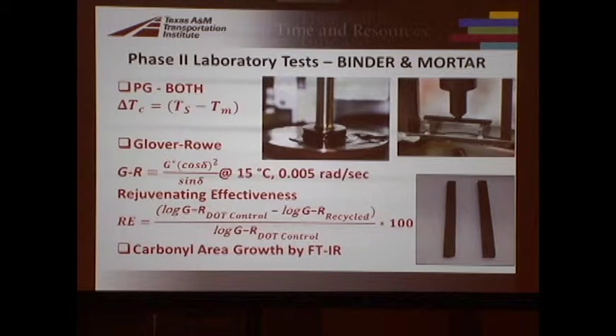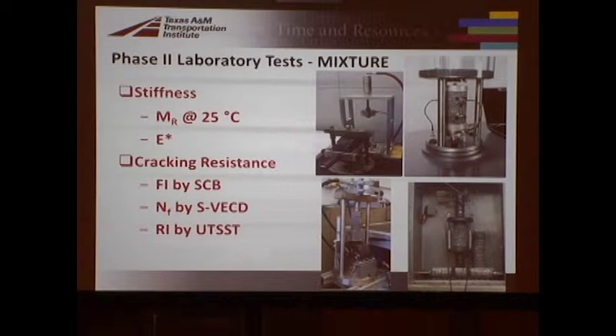So just how much do you improve over the DOT control? We would track that with aging, and you're going to see how aging definitely affects it. And then, of course, in addition to rheology parameters, we're also looking at chemical parameters, such as oxidation measured according to carbonyl growth by FTIR. We're also doing mixture tests. So we're doing binder, mortar, and mixture tests.